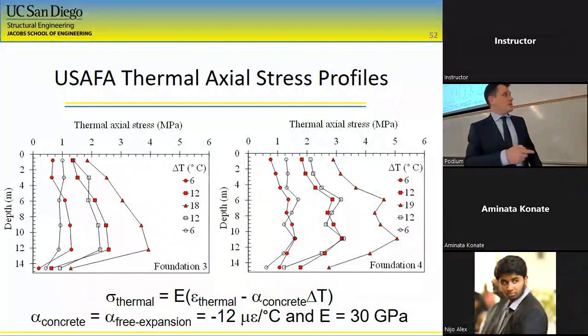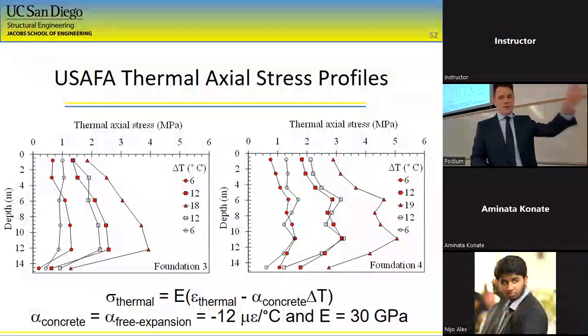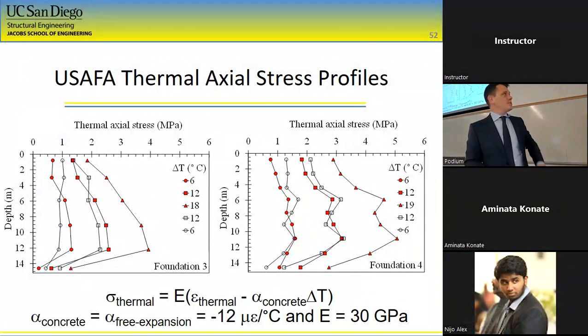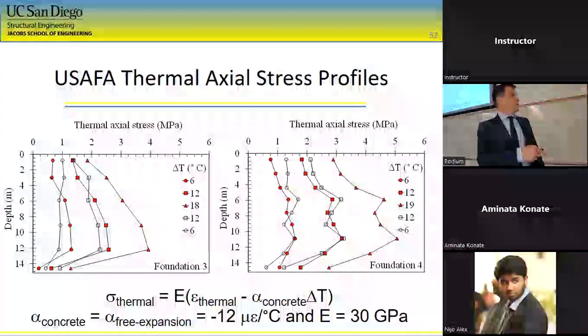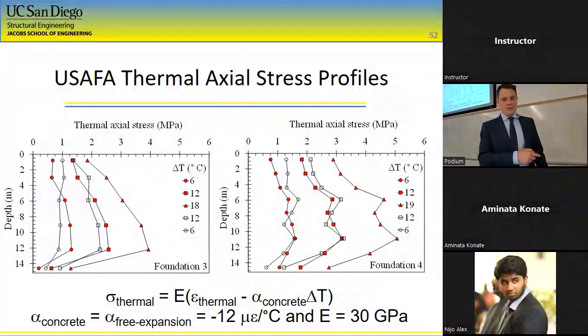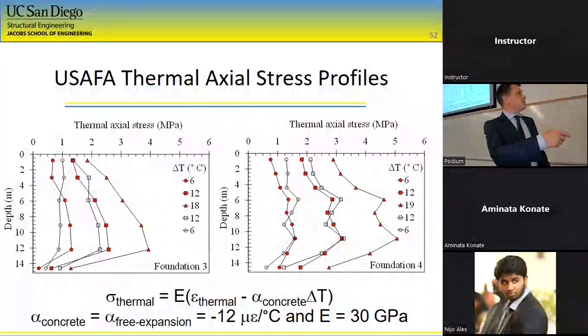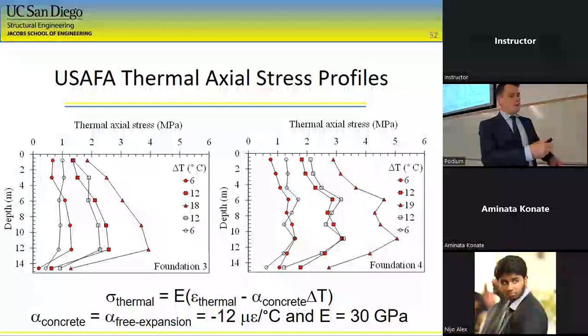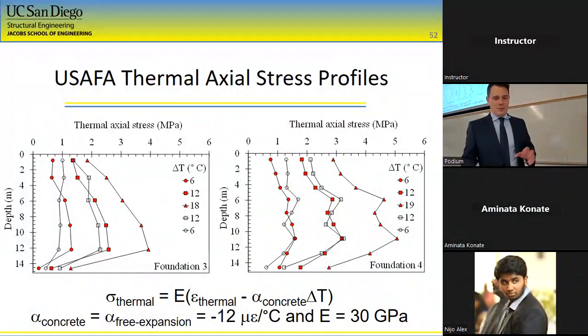Then we convert those to stress using this equation here. So we measure the thermal strain and then subtract off the free expansion thermal strain and multiply by the Young's modulus, which gives you the thermal stress. And you can see that the stress increases with depth up to about 4 to 5 MPa. But then at the toe, because it has poor cleanout, the stress was much smaller. So this is the effect of having that loose sand there. So inadvertently, we created ourselves a challenging soil deposit.